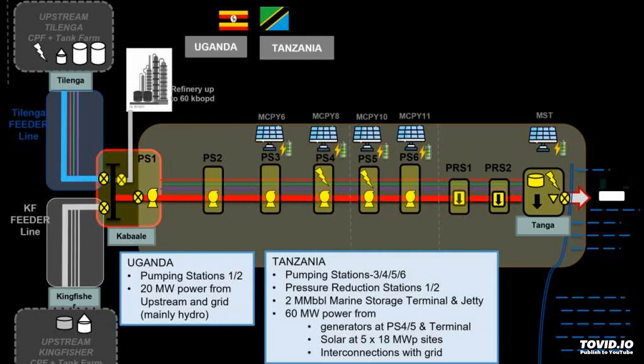In order for flow to be maintained, the EACOP has to be maintained at a temperature of at least 50 degrees Celsius. Testing showed that if the crude oil is flowing at high rates under high pressure, initial heating at the pipe head to 80 degrees Celsius will be enough to keep it moving, as the rate of cooling is so slow it remains above the 50 degrees Celsius threshold along its entire 1,443 kilometers. But if flow rates and pressure come down, it will cool more as it moves, threatening to solidify and block the flow. To get round this, two heating stations have been added to the design, capable of boosting the crude oil temperature back towards 80 degrees Celsius to ensure strong flow.